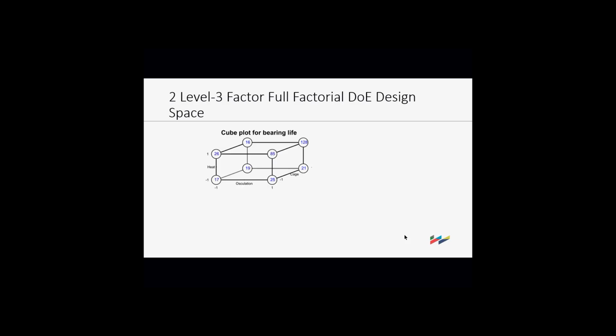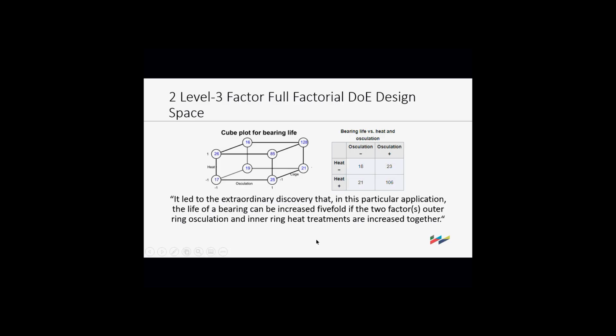Here's one of what they did on bearing life. In the technology they did, there was an interaction that they did not detect for decades, that they didn't know about. What they were looking at was osculation and heat. And it wasn't linear. If you controlled both of them at the same time by raising them, you didn't get just double, you got a 5-fold improvement in life. So, a 5-fold increase, and they were missing a very important interaction that was going on.